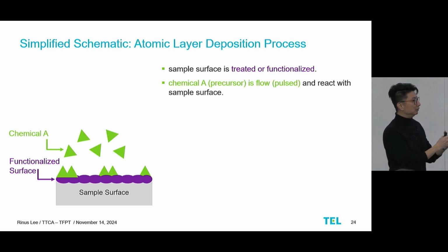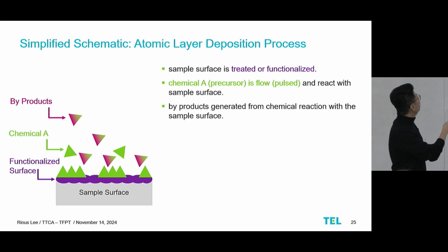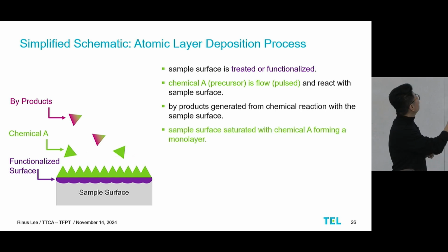flow into the chamber itself, or we typically call it a pulse. And then this chemical A, these green triangles, will react with this sample surface here, forming some sort of a reaction. What happens next is, by forming a reaction with this sample surface, of course there are some byproducts that are going to be generated, denoted by these pinkish green triangles. Further on, the sample surface eventually will be saturated because all the chemical A's will be on this surface itself, and there's no longer any site for chemical A to land on the sample surface. So this saturates and forms a monolayer on this surface itself.